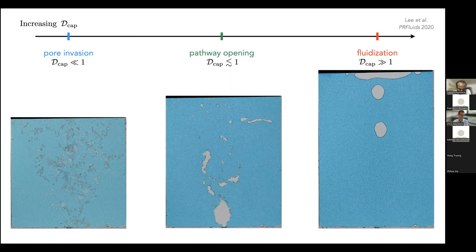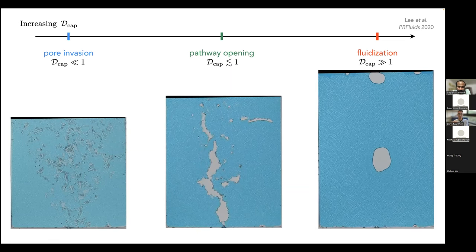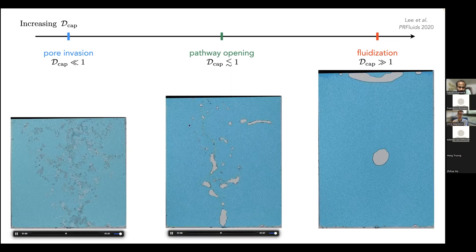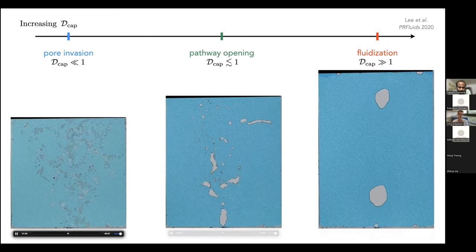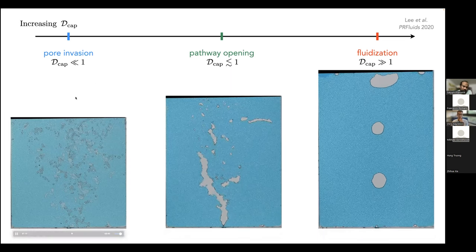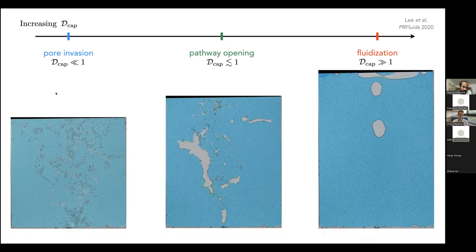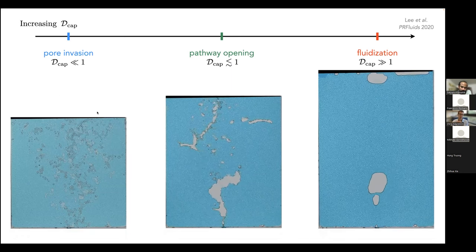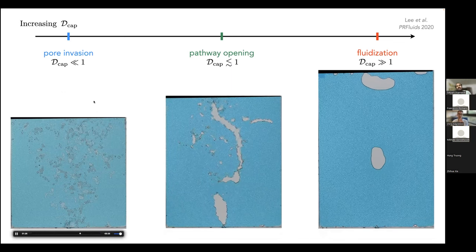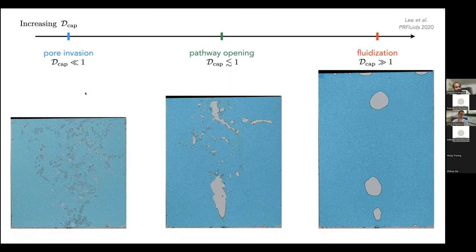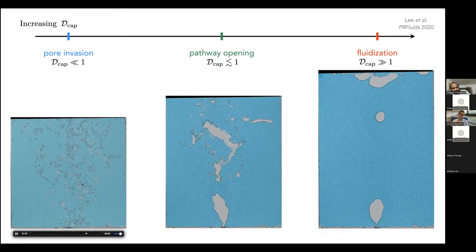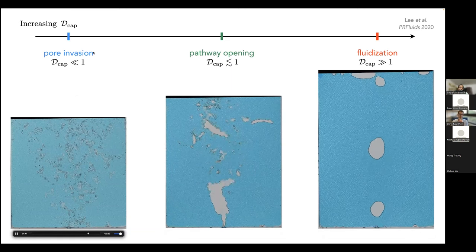Yeah, that's a good question. I think in a way the key feature that our model has that standard two-phase Darcy flow doesn't have is the distinction between the video on the left and the other two, which is the fact that in the video on the left, all the gas is in the pore space. If you wanted to model that problem, you would probably use the standard modified Darcy model for two fluid phases and a rigid porous material, where you characterize the capillary pressure function and the relative permeability functions as functions of saturation in the medium. That lets you make macroscopic predictions, which work okay. So in some sense there is already a model for this problem that at least describes what's going on, although I agree with you that in this particular experiment it looks a little bit more like percolation than like a continuum flow field.